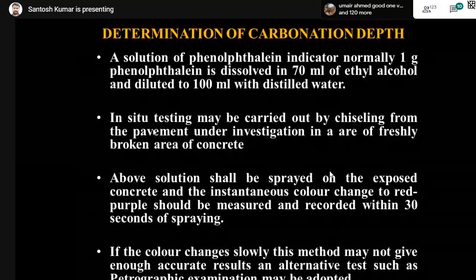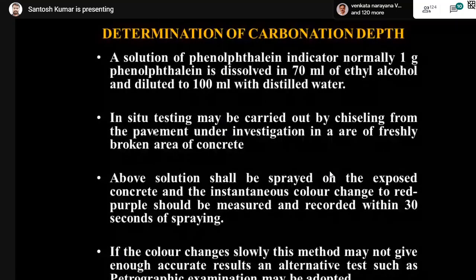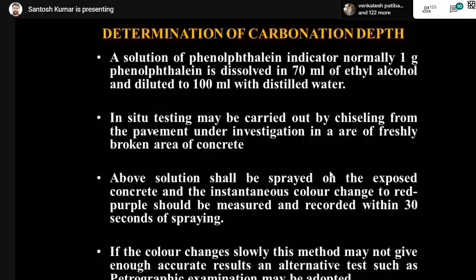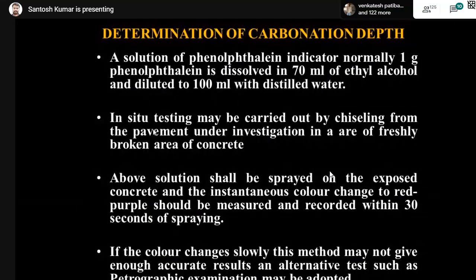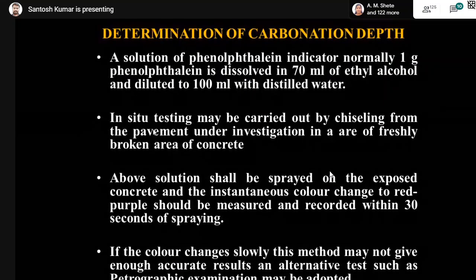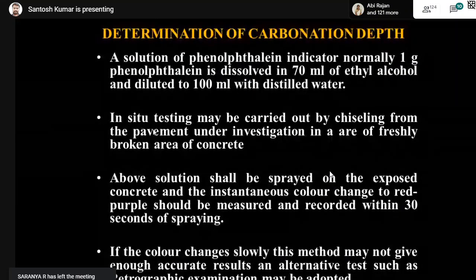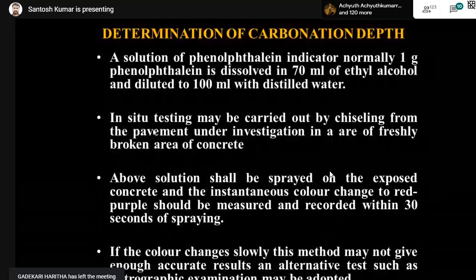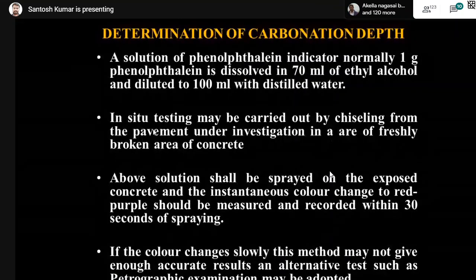A solution of phenolphthalein indicator, normally 1 gram phenolphthalein is dissolved in 70 ml of ethyl alcohol and diluted in 100 ml of distilled water. In situ testing may be carried out by chiseling from the pavement under investigation a freshly broken area of concrete. Above the freshly broken area, the solution shall be sprayed on the exposed concrete and the instantaneous color change to red-purple should be measured, and this should happen within 30 seconds of spraying. If the color change is low, this method may not give accurate results of carbonation. Alternative tests like petrographic examination should be adopted.